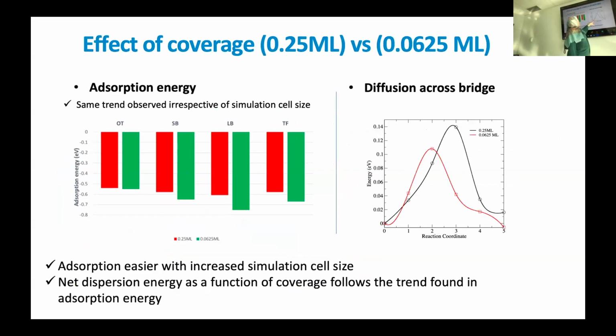But then what was really important is, again, the effect of the slab, the coverage, right? So here when we have 0.25 monolayers of H2S and here when you have 0.0625 monolayers. If I'm not mistaken, this is 3 by 3 and this is 4 by 4 in this case. So you see that it has an effect, but for H2S the dissociation barrier is really very low. It's on the order of 0.1 electron volt. So now, how is this affecting the entire picture?